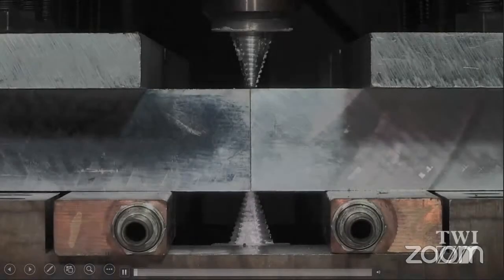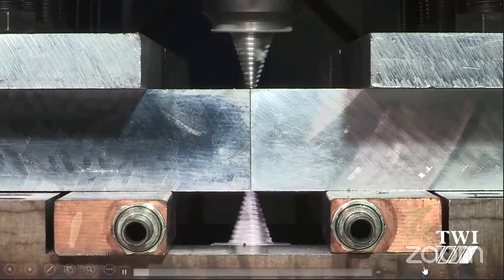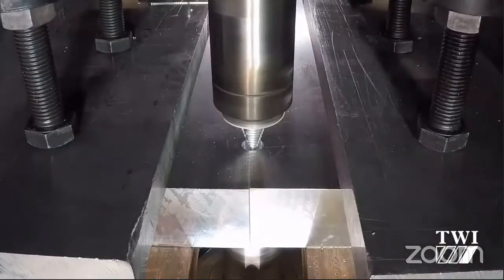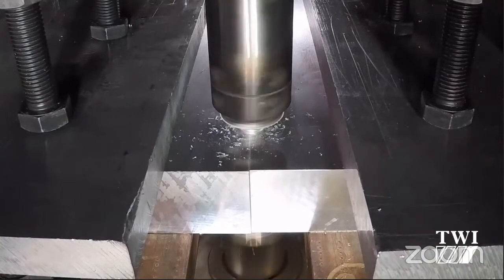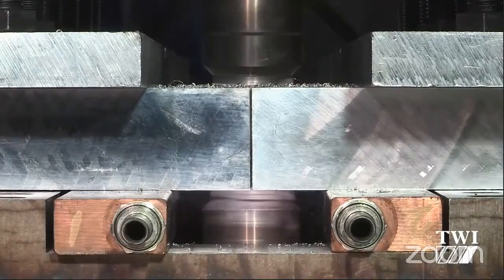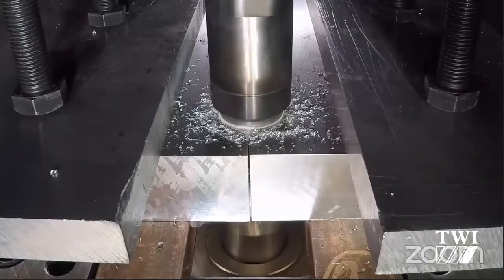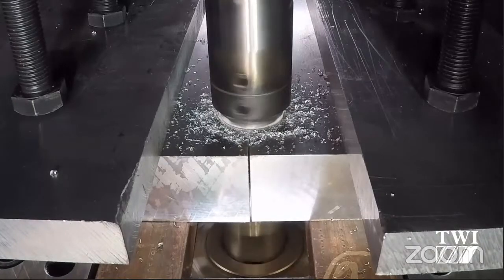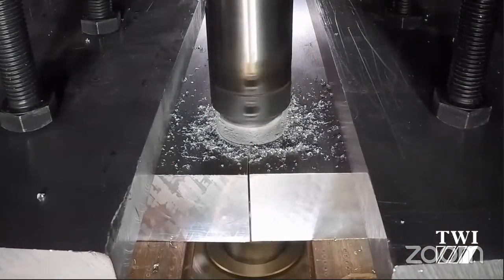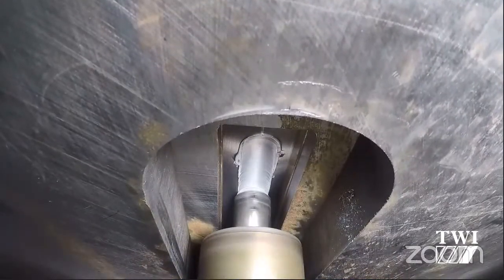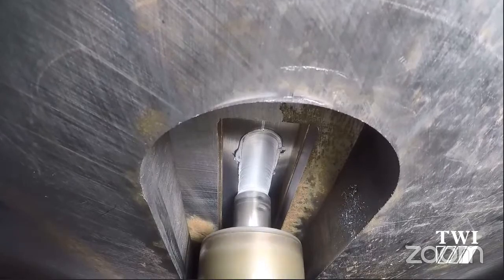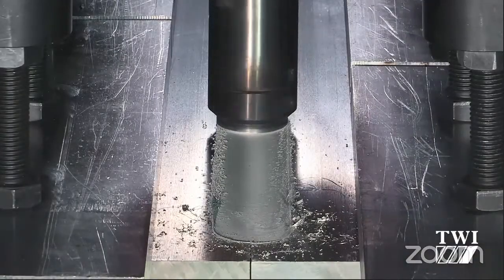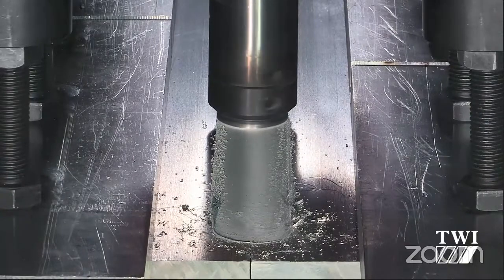So this actually shows the process in use. This is a video which shows two pieces of aluminium being joined. The aluminium is 50 millimeters thick, and we're welding it from the top and the bottom simultaneously. Because we're not getting any melting, we can weld in any position, including directly overhead. We're seeing the two tools embed themselves into the aluminium. The aluminium internally is now very, very soft, and we can stir it together by moving the tools along through the aluminium. As I mentioned, we can weld upside down because we've no liquid metal there. It's still solid, and so we can weld in any position. That also means that we can weld underwater as well, because the water does not get into the weld zone.